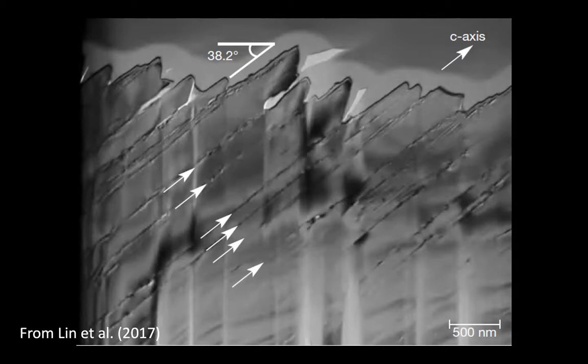And it turns out the second stage here must have been a hydrothermal alteration, that some fluids percolated through the cavities in which these quartz crystals were contained. And those fluids etched away the surfaces and even were able to eat along the Brazil twin boundaries themselves. So these boundaries that we're seeing here, they're not really beautiful Brazil twin boundaries. They're really boundaries with lots of little fluid inclusions left over from this etching event. And once that happened, now you have the conditions for the kind of reflection and constructive interference that will lead to diffraction.